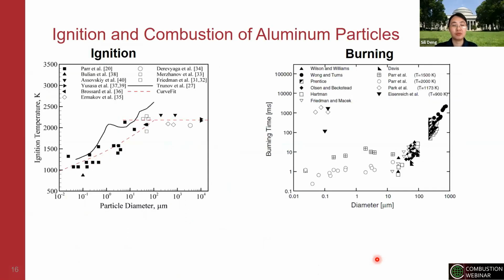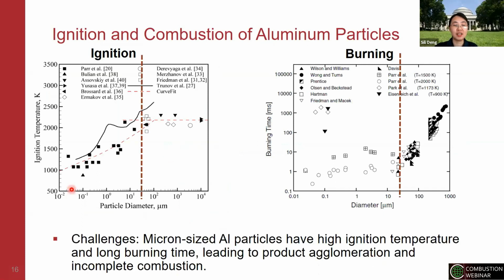But first, let's go through some of the issues of aluminum combustion. The main issues are the ignition and combustion. And basically, you can see as the diameter of the aluminum particle changes, actually the ignition property deteriorates, right? You need a relatively high ignition temperature compared to the gas phase reaction that we are familiar with. And the burning time actually increases by orders of magnitude as the size goes from the nano size to the micron size. And the dashed line here actually shows in practice, we normally use aluminum particles larger than 20 microns or 50 microns-ish. We are far away from the nano-sized particles.